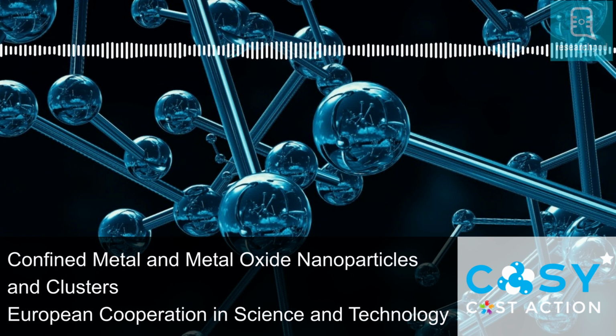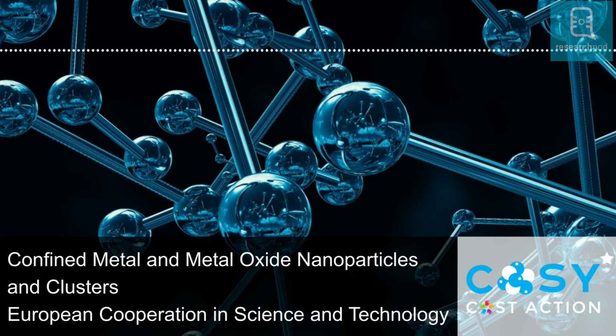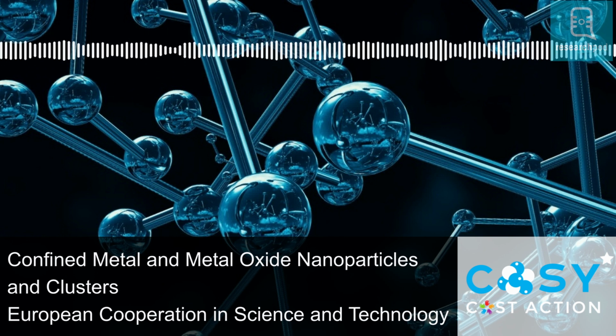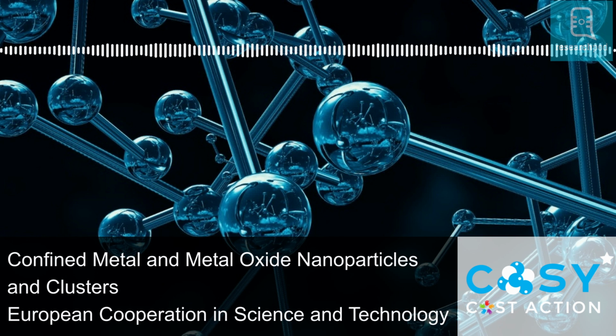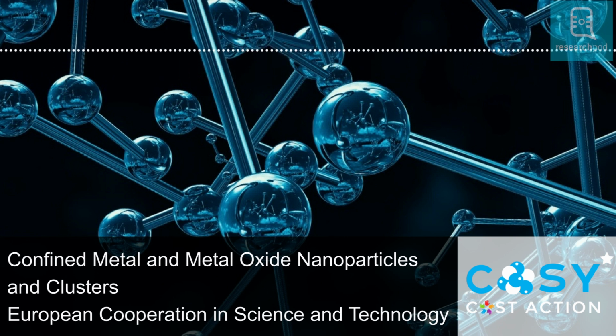They also showed, both experimentally and via their theoretical models, that when the adsorbed oxygen molecules vacated the clusters, then the copper 5 clusters were able to reclaim the donated charge and resist oxidation. This could offer a vital way forward in terms of optimizing their catalytic performance.